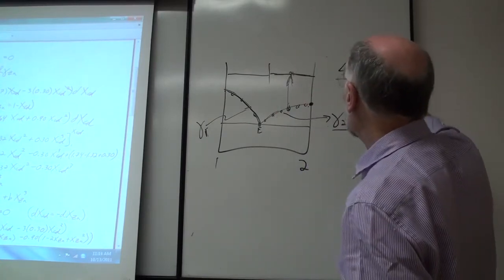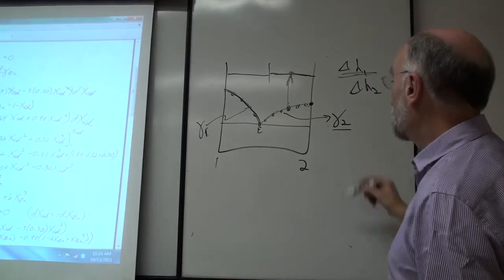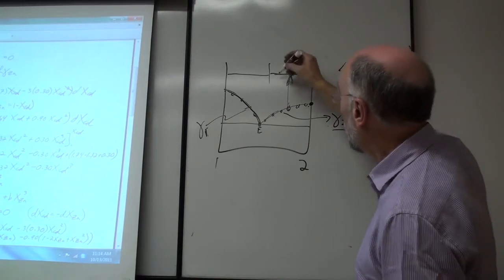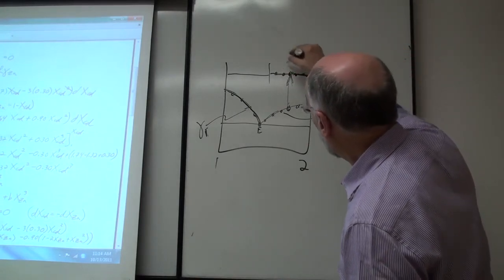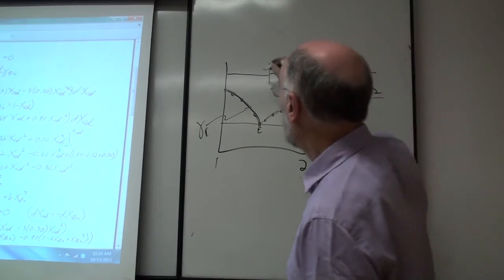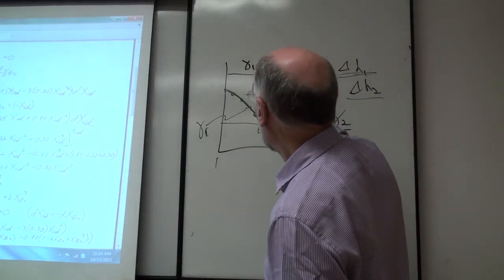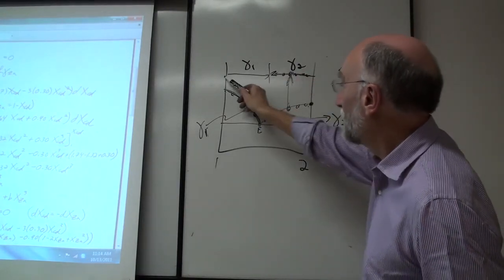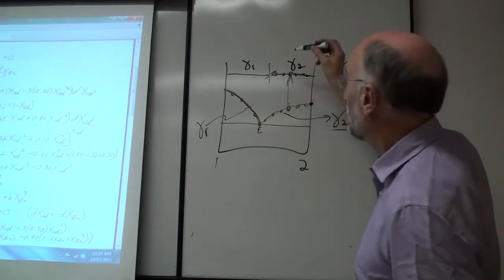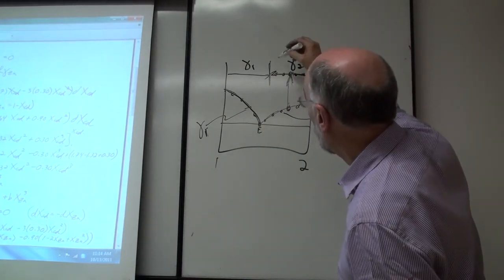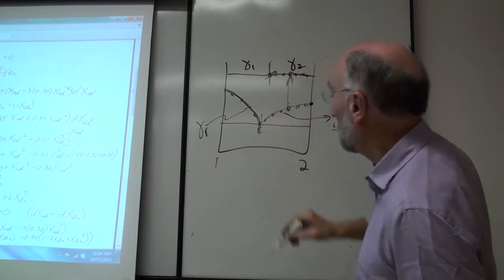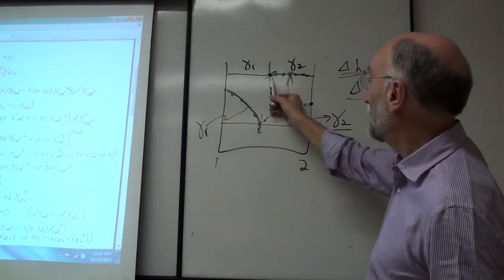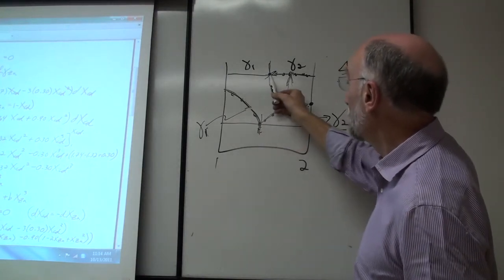So let's say the heat of mixing is known, so the partial heats of mixing are known. You get gamma 2 on the liquidus, you then go up using your partial heat in the Gibbs-Helmholtz equation, and you end up with gamma 2 over this region, and gamma 1 over that region. Now, you've got gamma 2 over this region, you've got gamma 1 over this region. So gamma 1 and gamma 2 are both known at this point. Okay, so now you're okay, because you're using this point as an endpoint for the integration of gamma 1 and using this point as an endpoint for gamma 2.